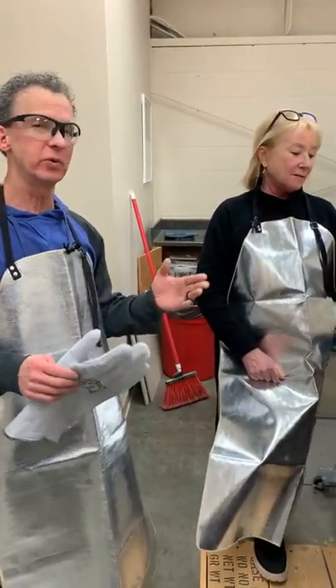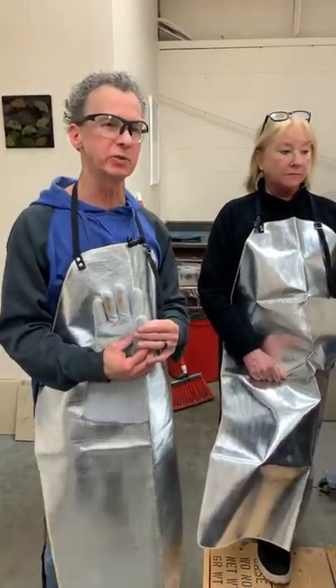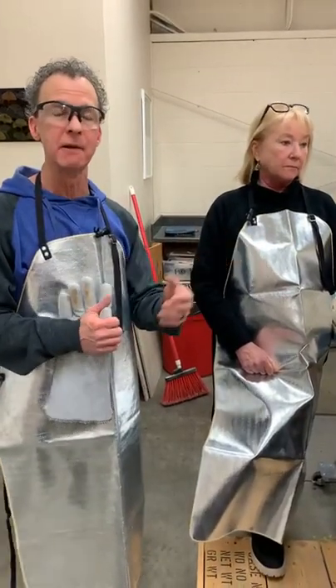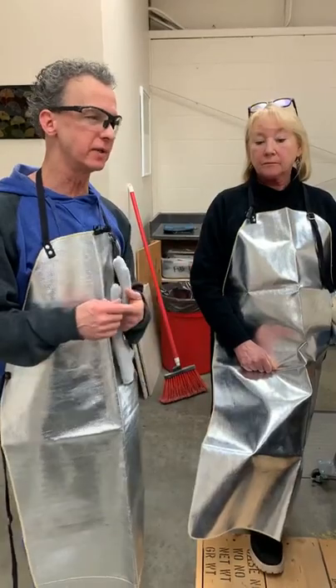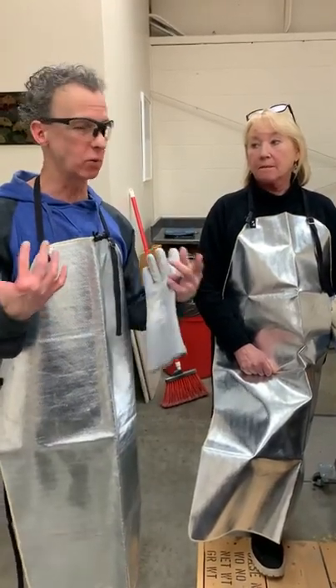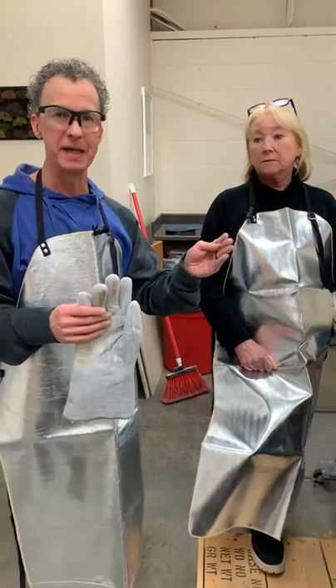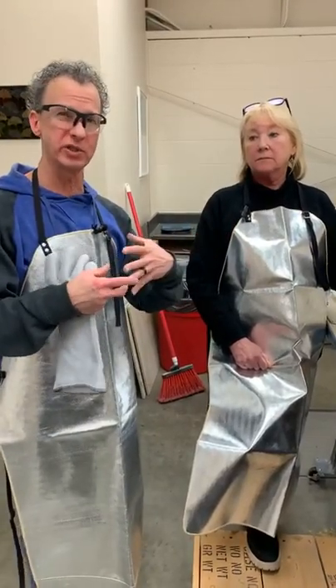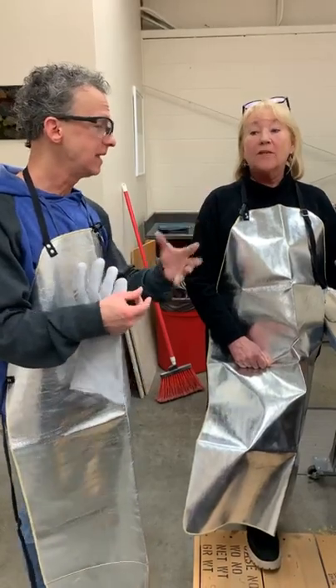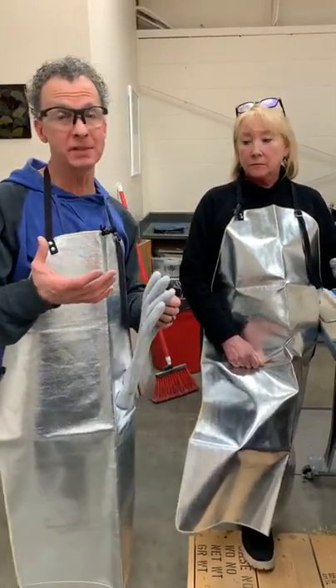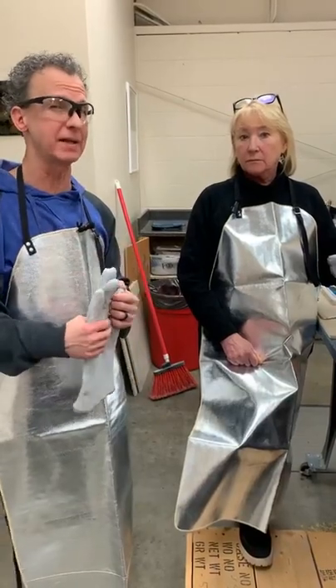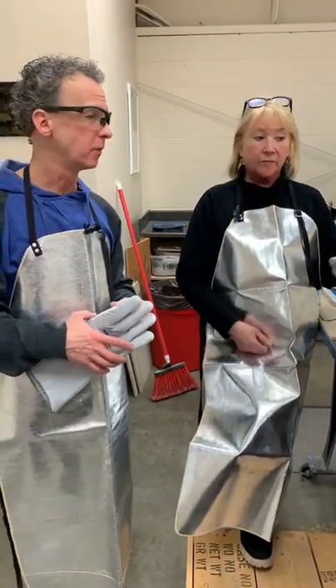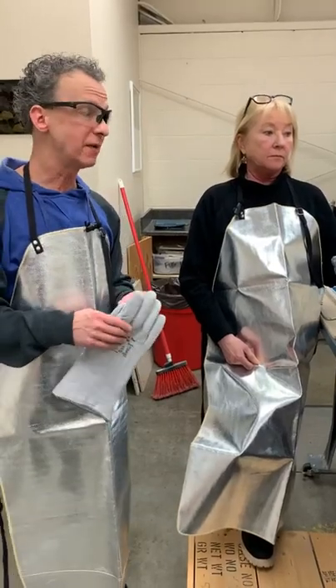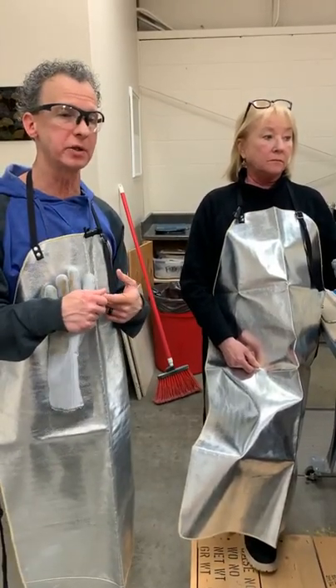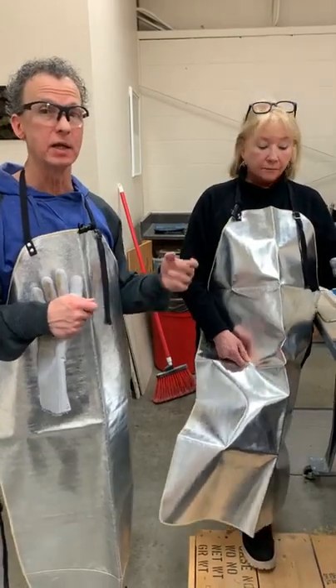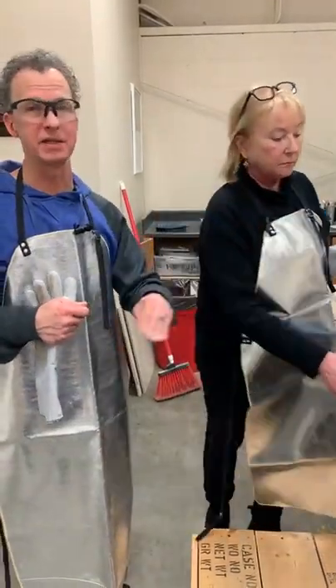I'll mention real quick the risk of getting too hot. Some people ask, well, why not just go hot all the time? The simplest issue with going too hot is that sometimes, especially with warm colors, you can change the color of them. I don't know if you've ever noticed that yellow shifts to orange, orange shifts to red, red shifts to black when they're hot. Sometimes if you get too hot, they don't always shift back as nicely as you might like, where your reds can end up kind of brownish. What definitely does happen is that with warm colors that are transparent, they turn opaque. An orange will turn opaque every time at these temperatures.